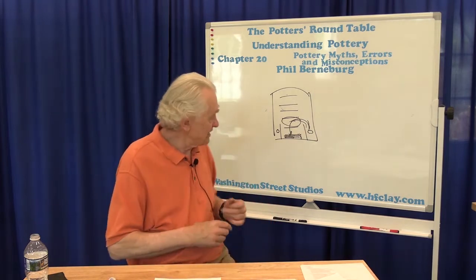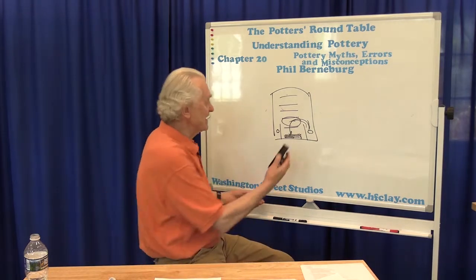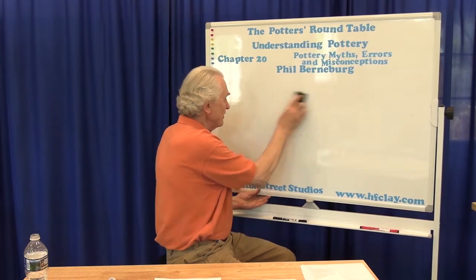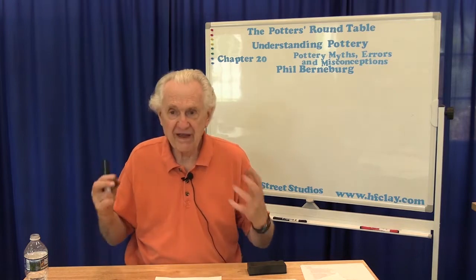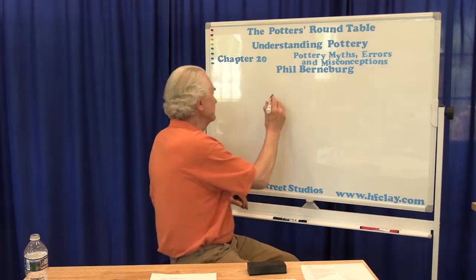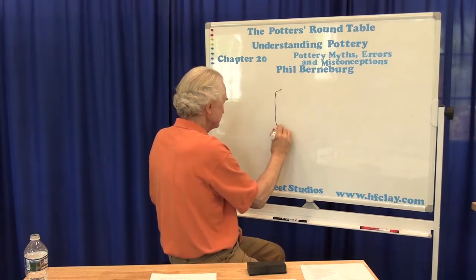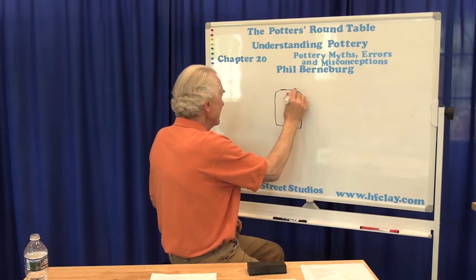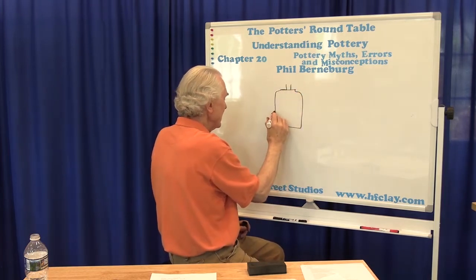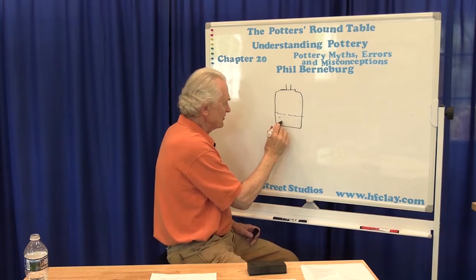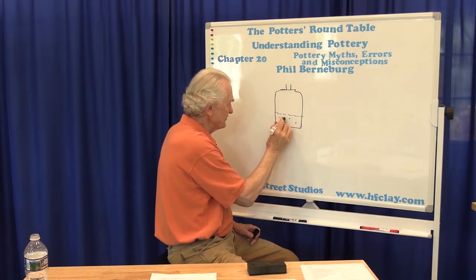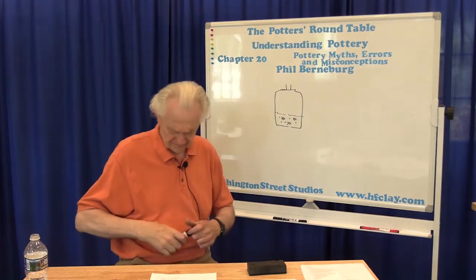Okay, again, a subject related to gas, and this is specifically propane, is that one of the thoughts is that the propane tanks, as you're going along in the firing, freeze up and cause low gas pressure. What they typically mean is that you've got a propane tank, and you may see a line along the bottom where moisture condenses, but you actually may get frost condensing on the bottom, the outside of the tank.